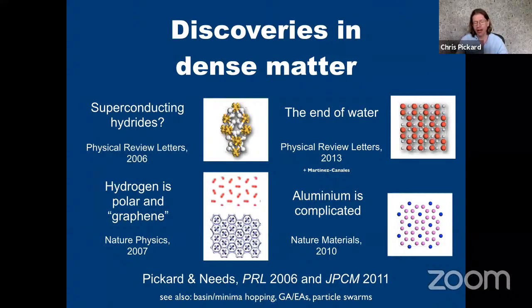aluminium was a pressure shock reference equation of state. But we found, and it wasn't anticipated before, that there were additional phase transitions in aluminium: when you exceeded a few terapascals, aluminium would adopt what's known as an electride phase, where electrons started pooling between the aluminium ions, forming essentially an ionic structure, but with no counter ion. It's all done itself, and the pooled electrons in the little interstitial regions become the anions. And so they can adopt much more complex structures than you would have if you just had an element behaving as a normal element.